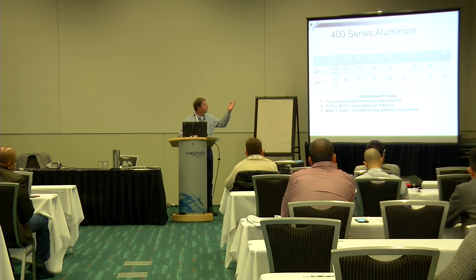Okay. 319, now that's more of a casting alloy. And your zincs are 1.0, and 380 is 0.1. So you have a variety in there once you get into that range. 400 series, you're picking up, look at the silicons in that, 11 to 13 in the 413. That's a lot. Okay. And you're picking up some copper and the rest. They're not quite trace elements, but they're not that high. So it's not, we can live with that.